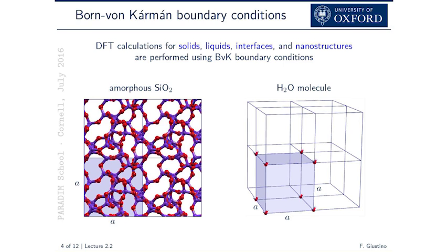This is not a problem because if you are careful enough and you use a large box, these molecules will not interfere with each other. So if the wave functions do not overlap, you are fine. So typically, if you want to study a finite system like a molecule or an atom, you place this in a box, you choose a size, which is maybe a few times the linear size of the molecule. You perform a calculation, you look at the property you want, and then you double the size of the box, you calculate it again.